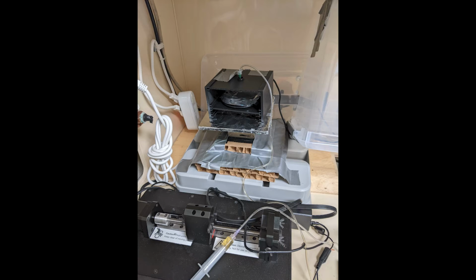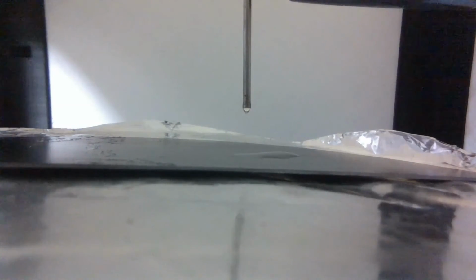All systems functioned as expected, but due to problems with the solution tubing, a stable Taylor cone could not be formed, and the deposition was unsuccessful. The next tests were performed with the full system to increase the stability of the Taylor cone. Subsequent tests performed had a much more stable Taylor cone, although there were a few drops which meant that the deposition was not fully uniform across the substrate.